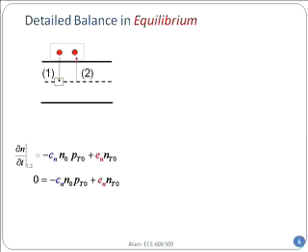Okay. Now, once I have this, I know if I somehow could find out this N sub T and P sub T, all those quantities, and I'll show you how to, then a beautiful relationship between these two, and detailed balance says that E sub n, the emission coefficient, is actually related to the capture coefficient. You see, it has to be. If the total thing has to be balanced, then the rate at which you capture must have some relationship with the rate at which you emit. And this detailed balance will allow you to connect the two coefficients.